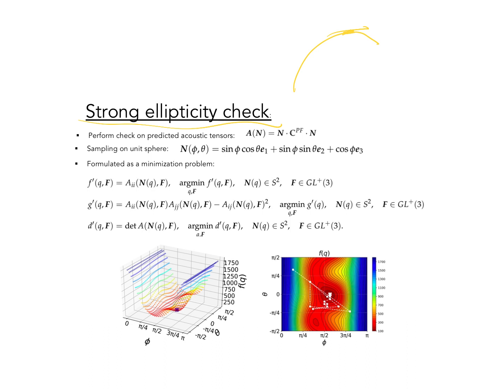If we propagate a wave, we need the acoustic tensor in small strain, which is the normal vector times C times the normal vector, to be non-singular. If the acoustic tensor is singular, then your elasticity problem will have a problem in the sense that the wave speed actually vanishes.